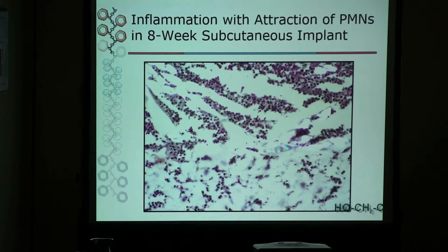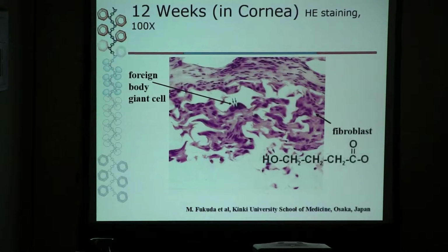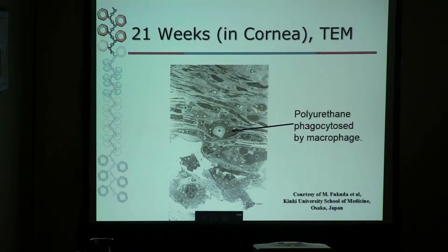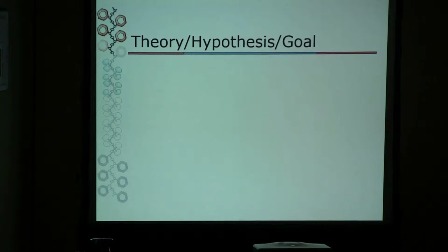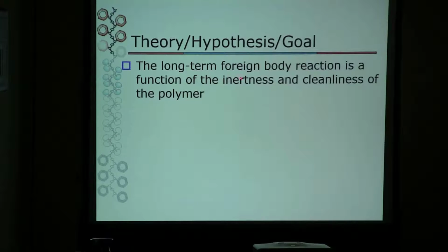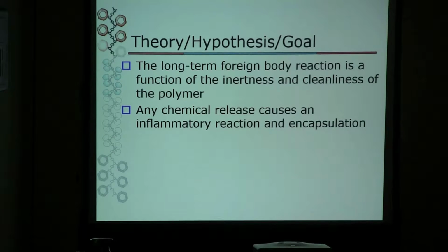What I found very intriguing was you had a huge inflammatory reaction that attracted polymorphonuclear leukocytes. And if you follow it, you'll see foreign body giant cells. And if you look at it in different areas, you can see phagocytosis of polyurethane fragments. And the more of these granulocytes that were attracted, the larger the capsules were that formed around the implant. So the theory was that the long-term foreign body reaction is a function of the inertness and cleanliness of the polymer. Any chemical release causes an inflammatory reaction and exacerbates encapsulation.